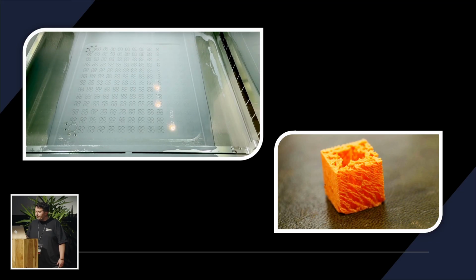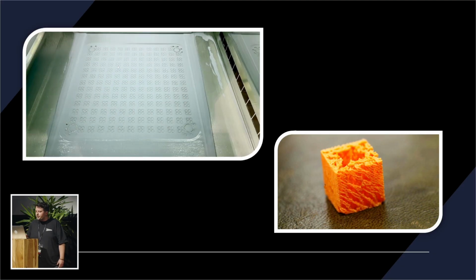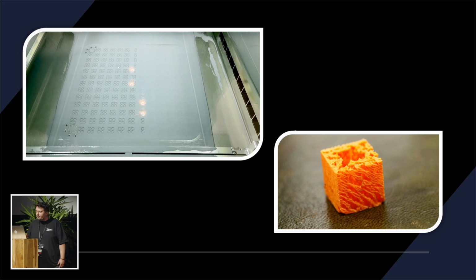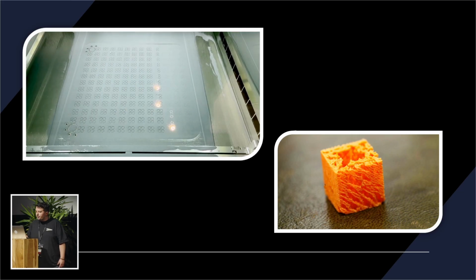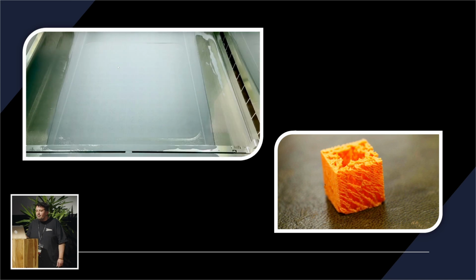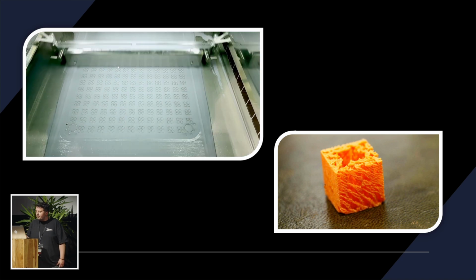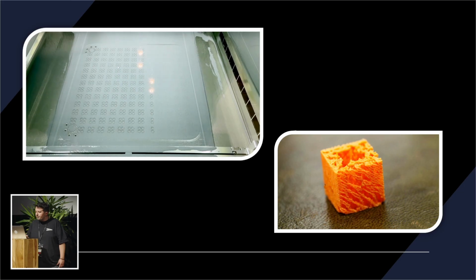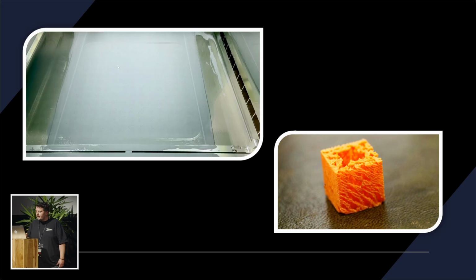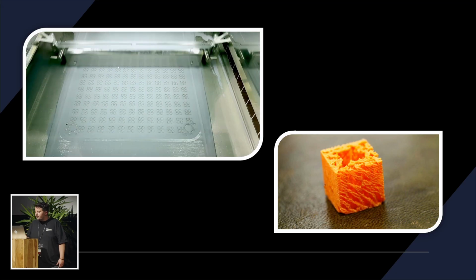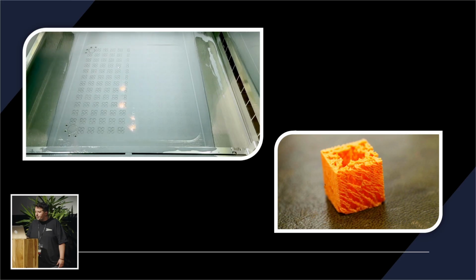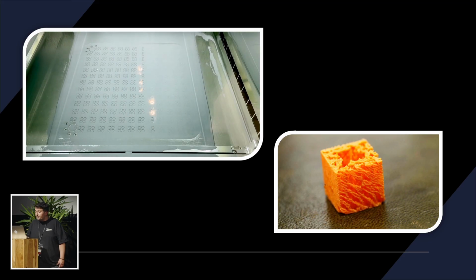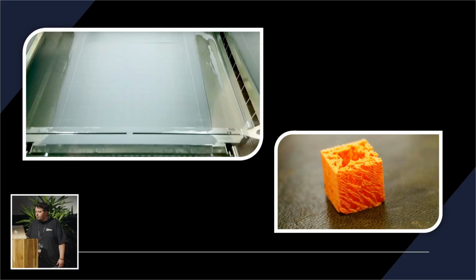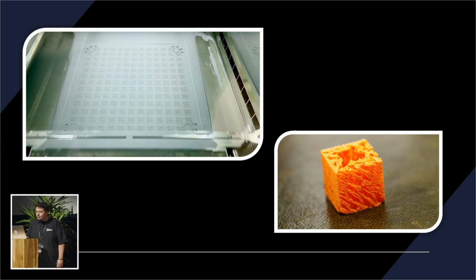A common cause of print failure can be down to material health. Some plastic filaments are very susceptible to absorbing moisture from the environment, and some are negatively affected by UV light, so need to be stored and looked after carefully, just like resin for SLA prints. And this is much the same thinking when dealing with metal powders. There are different reasons for poor material health, but if you keep the metal powder in a sealed container, keep a constant temperature, reduce exposure to oxygen and moisture, you're going to have a much better time of it. And if your build does fail, you can save lots of time with your diagnosis of the problem if you can already rule out a few potential causes.